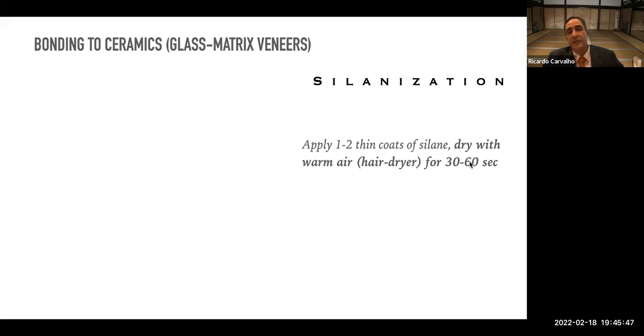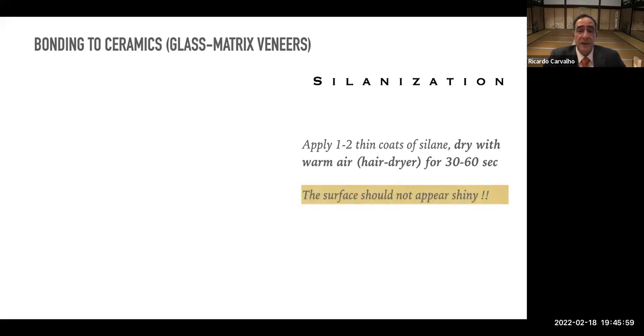Why we do this, of course, it is not something that you must do, but you will see that doing this, you are going to improve the bond strength to your ceramic. What is really important after applying the silane is that the surface should not appear shiny. If I have a veneer in my hand and I silanize it and I show it to you, you should not see anything. The comparison between non-silanized and silanized surface should not be different.